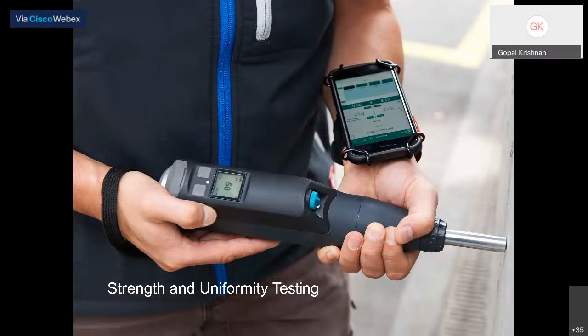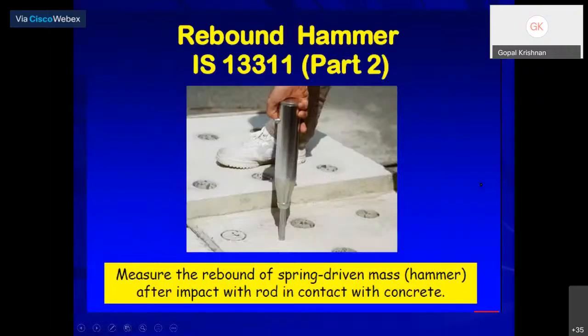One is the Schmidt hammer. It's very simple and very useful. We can get the in-place uniformity of the concrete. Very easy to use, mostly in the field, and this can be used to study uniformity of the concrete. The surface condition, presence of rebar and presence of subsurface voids can affect the test result. The standard is IS 13311 Part 2, and the principle is measuring the rebound of a spring-driven hammer after impact, with the rod in contact with the concrete surface, as you can see here.